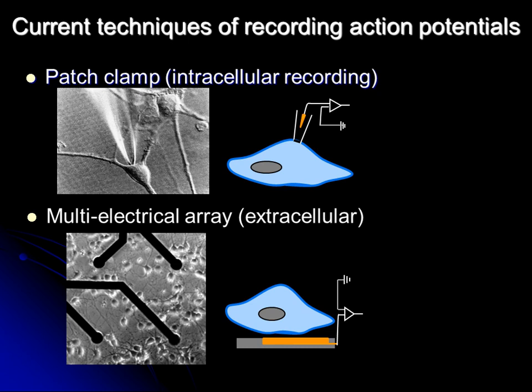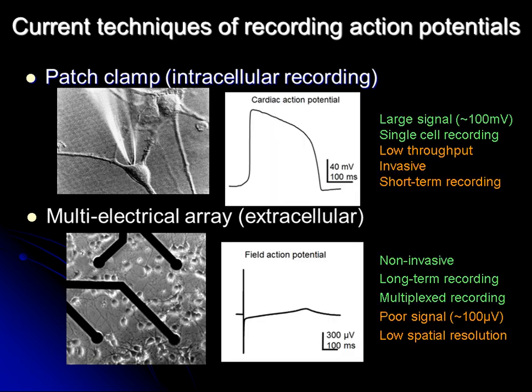Those intracellular and extracellular recordings have been around for a long time, and both of them have very complementary capabilities. For intracellular recording, we record a large signal, generally around 100 millivolts, and we know exactly which cell we record from. However, it has extremely low throughput. We're recording most of the time one cell at a time, maybe a few cells a day. And the recording kills the cell after tens of minutes.